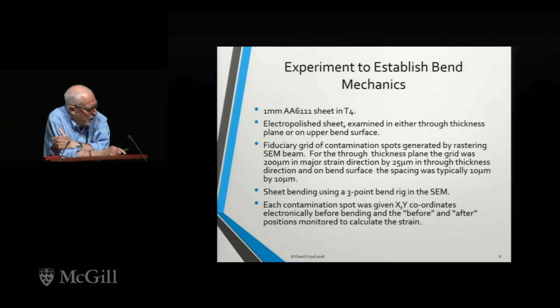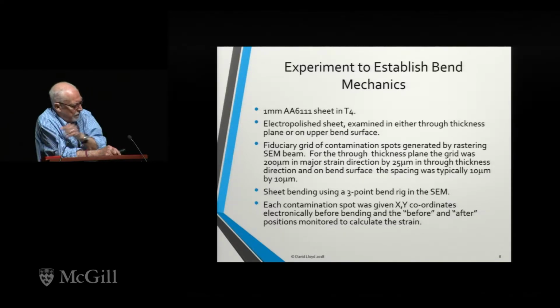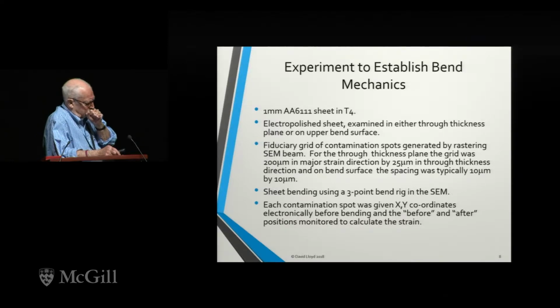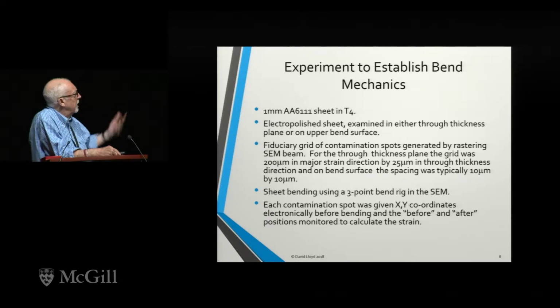For the basic mechanics equations, we used a grid that was 200 microns in the major strain direction and 25 microns in the through thickness direction. But for looking at the upper bend surface, which I was also interested in, what was going on in terms of the plasticity and damage there, we looked at a grid that was 10 by 10 or even 5 by 10. The sheet bending was done inside the SEM, using an automated 3-point bending rig. Each contamination spot was electronically given XY coordinates, which allows us to know where the spots were before and after bending, and so we could back out the strain.